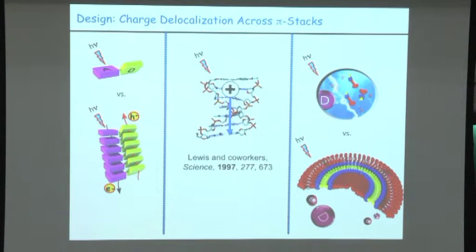The first effort that we took was to create a vesicular structure of the perylene imide chromophore, wherein you can have a donor that donates an electron to the stack. Injecting that electron, it makes sure that it takes a longer route before it recombines to give the neutral state. And that gives a sufficiently long lifetime for the charge-separated state.